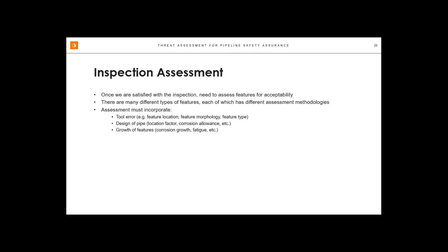Our assessment has to include things like tool error. Where was this feature located on the pipeline? Is it close to a girth weld that's going to introduce more error? What's the morphology? Is it like those pinholes where there's concerns that the tool didn't size it properly? What type of feature is it? Some inspection tools or some inspection technologies are not capable of picking up certain types of features. What's the location factor in that area? What's the corrosion allowance? Are those things there that are going to impact the acceptability criteria? How fast is the feature growing, if it's corrosion damage or if it's fatigue cracking?